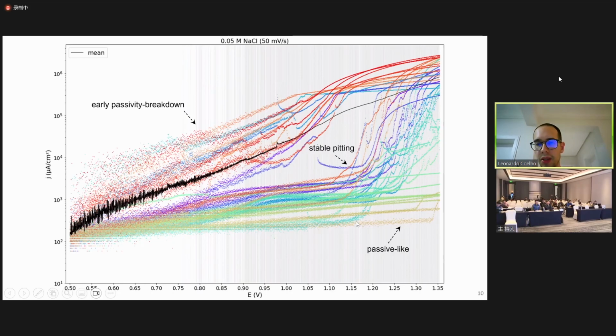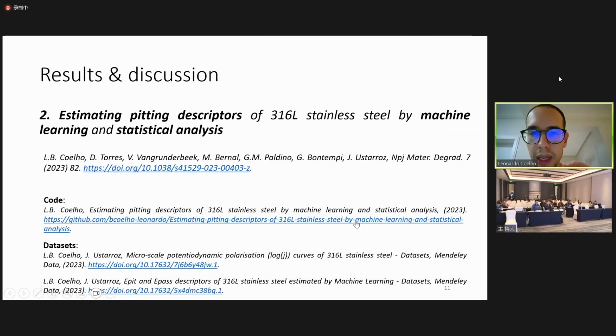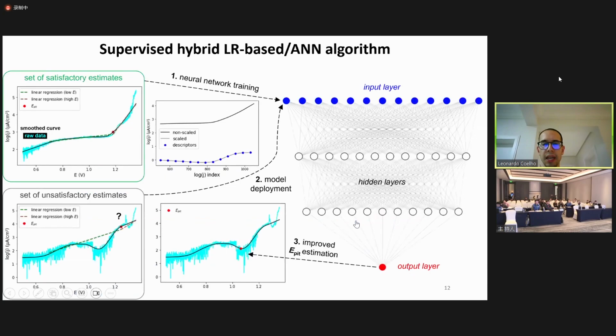So this opened the doors for our second study, in which we employ machine learning for estimating the pitting potential. In fact, the estimation of pitting potential is in principle a problem that can be solved by linear regression. It's simply this inflection point right there. But in corrosion, there's no really standard method for doing so, although you can follow an ISO. It often says it's the point where we have a sharp increase in current, but we don't have a numerical definition or a numerical standard for defining this very important parameter.